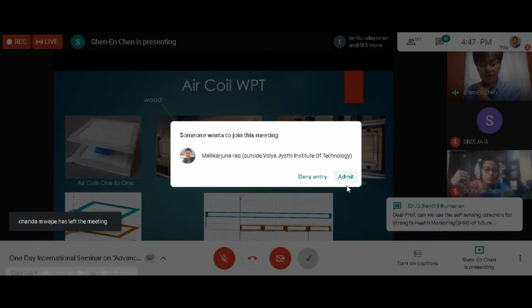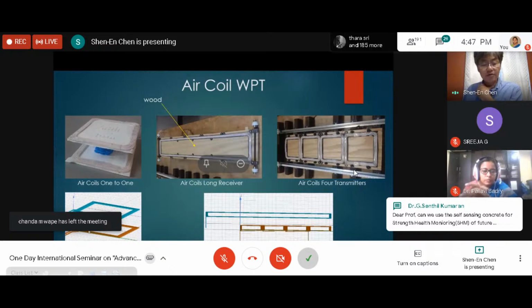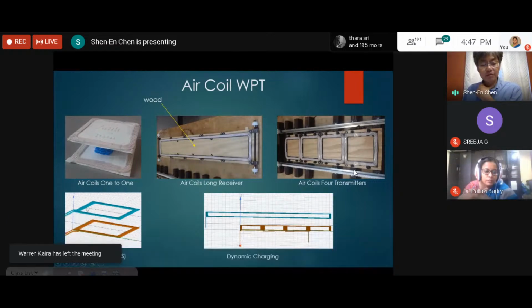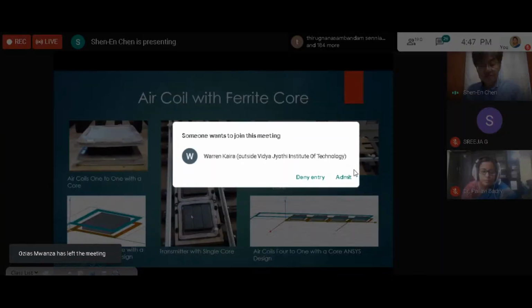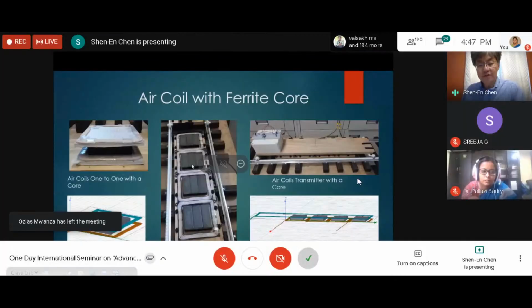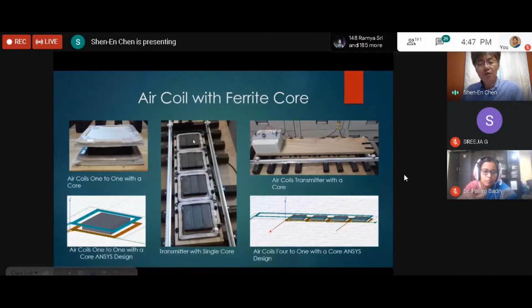This is what we call the air coil system. In other words, other than the litz wire, we only use wood plates to form the coil system. As you use the ANSYS modeling of the electromagnetic effects, you can model the litz coil system. And these black elements within are actually the ferrite metal material, if you will, which has a permeability of about 3,000.